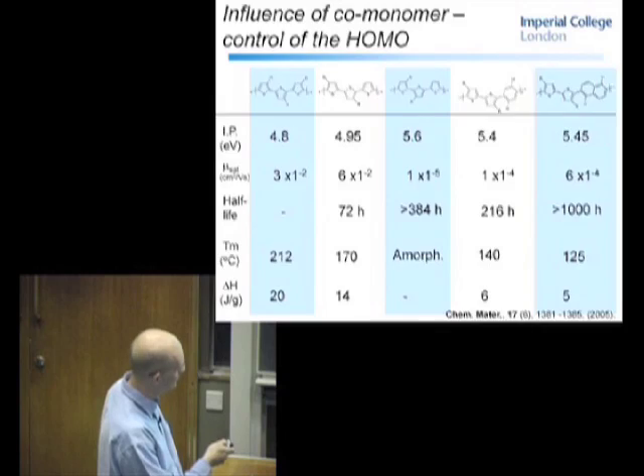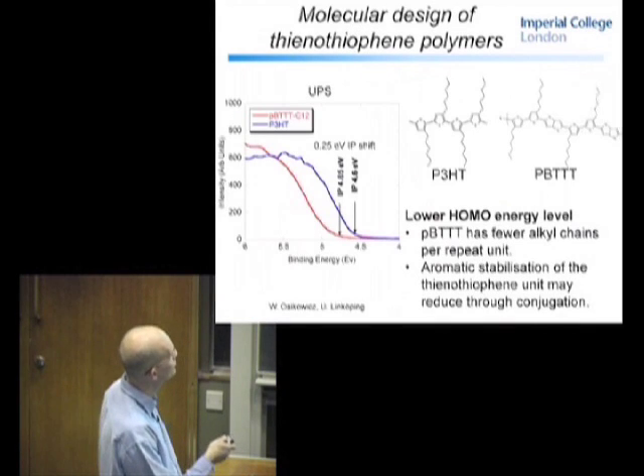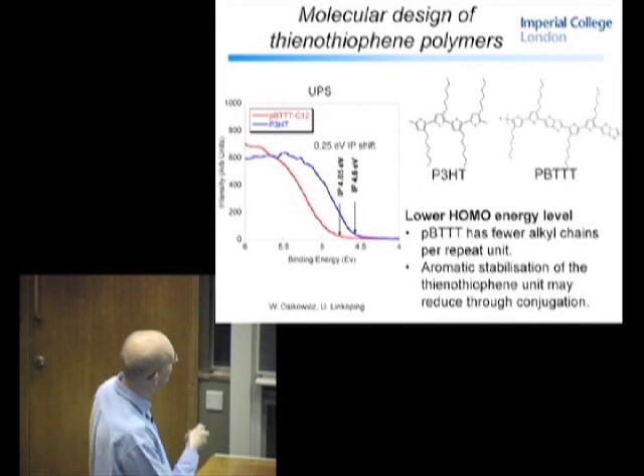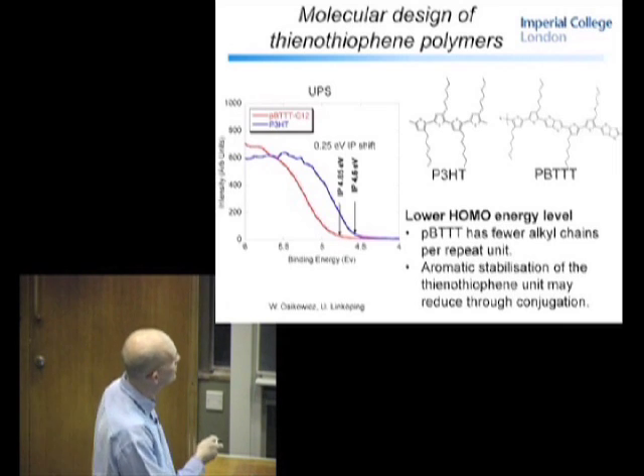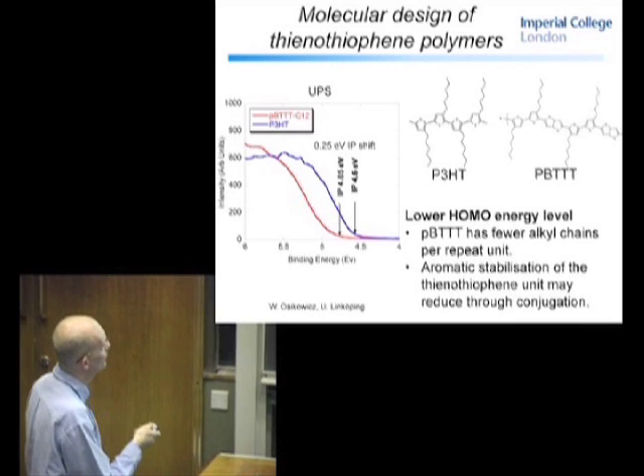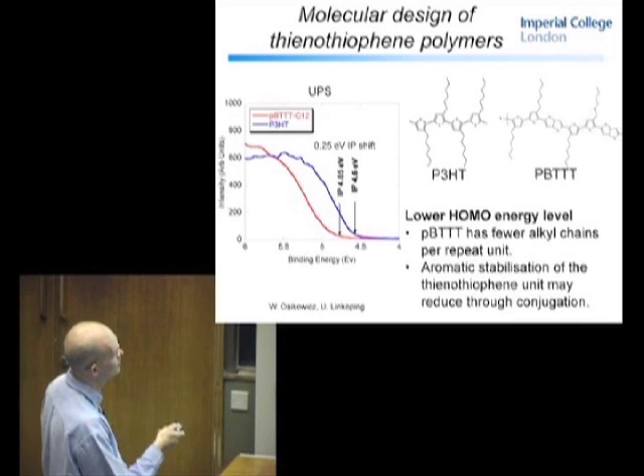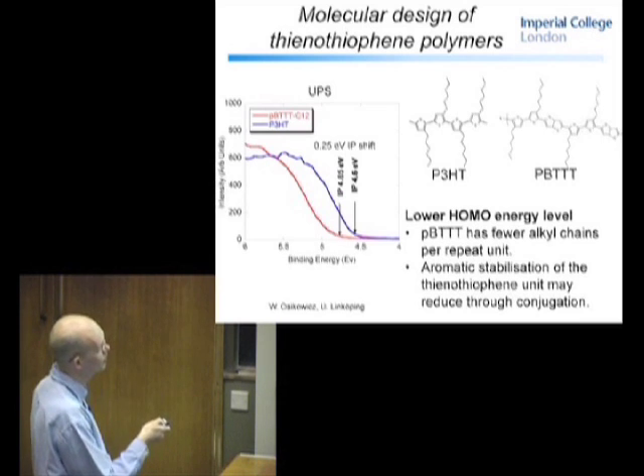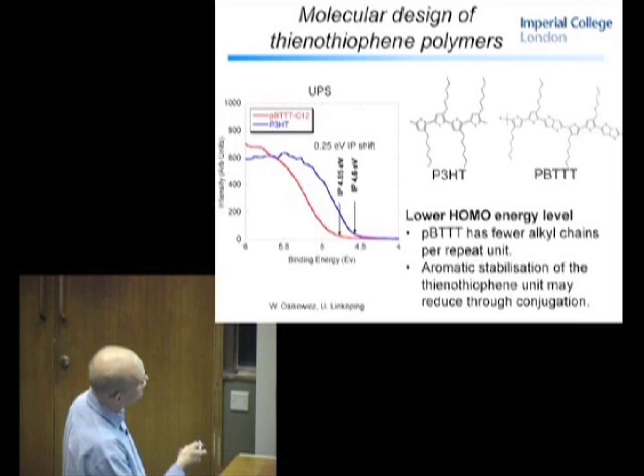But when we started looking at these thienothiophene polymer structures, we were able to shift again this ionisation potential higher. This is a UPS spectrum with the binding energy. You see here that we've increased ionisation potential by 0.25 electron volts. And the reason we're able to do this is because this is more aromatic. It stabilises through conjugation, not completely, but a little bit. And also there's no electron donating alkyl chain, so again the electron density is a little bit lower.